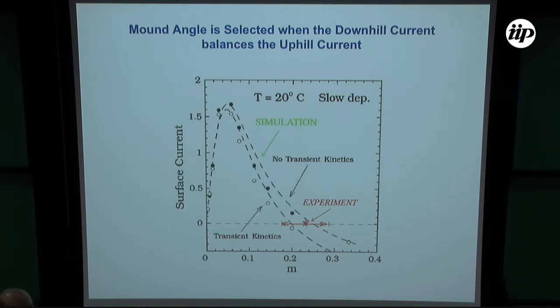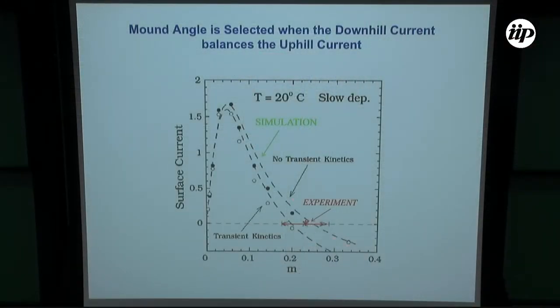The difference between the two curves is a little detail, but it's interesting to talk about. In one simulation, atoms are deposited, and if they're at the step edge, they go down. That's it. There's nothing extra put in. But in the other simulation, what we have put in is some kind of transient kinetic, some kind of funneling effect, meaning that there is some residual kinetic energy so that when an atom reaches the surface, maybe it can continue to go down one step, one layer or something like that. So instead of just stopping where it lands, it could move another layer down. There isn't much difference between the two, and the selected angle is very nicely in agreement with what you see in experiments.